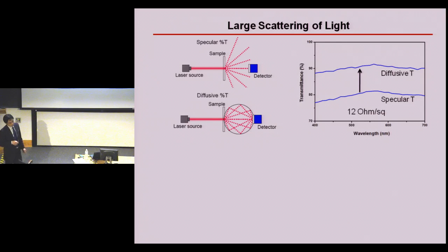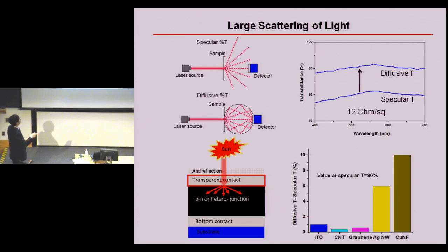So there are two ways to measure the transparency. One is called specular transmittance. So basically, you measure the direct transmittance in a very small angle distribution. The other way is to measure the forward transmittance, which includes all the forward light, using the integrating sphere measurement. So here we see, for the copper nanofiber-based transparent electrode with 12 ohm per square sheet resistance, we get a big difference between these two transparencies. And this 10% difference should be the forward scattering from the copper nanofibers. And this big difference will be very useful for solar cell applications.